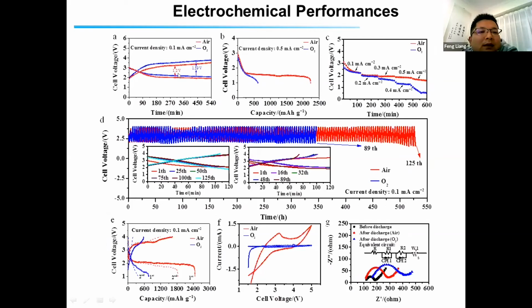So in the case of the sodium-air battery, the voltage gap is smaller than the sodium oxygen battery. So it's very interesting because normally the sodium-air battery is poorer than sodium oxygen. And also it has a large discharge capacity, and at different current densities it is better in the case of the sodium-air battery. Most important thing is this battery can be cycled for more than 500 hours. So the cycle performance is better than the sodium oxygen battery. And we analyzed the discharge capacity, also CV and the EIS results.